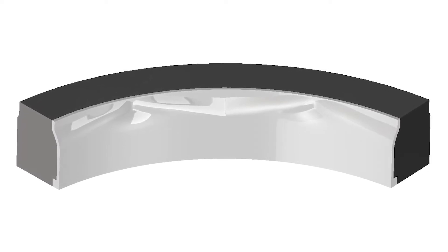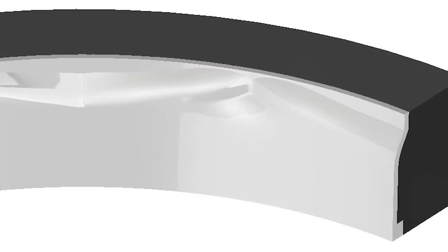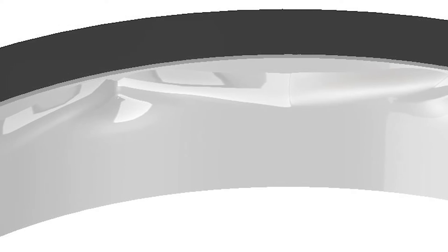A patent-pending process is used to accurately form the high-modulus plastic. The super-wide seals incorporate our patented enhanced lubrication hydrodynamic waves. These waves pump a thin film of oil into the dynamic interface during rotation. This reduces friction, wear, and seal-generated heat.